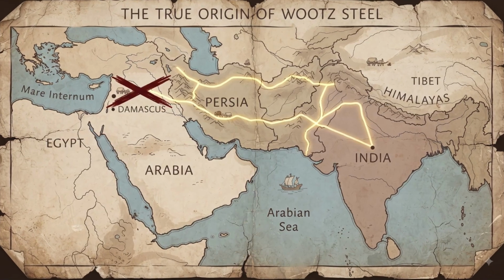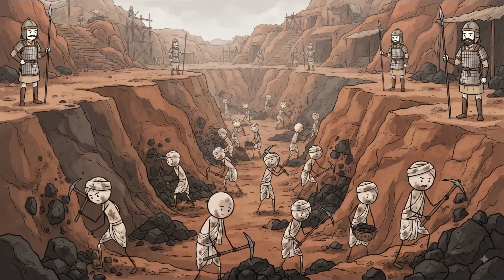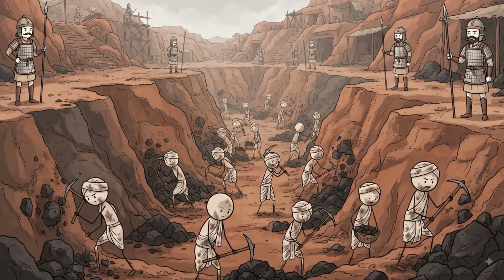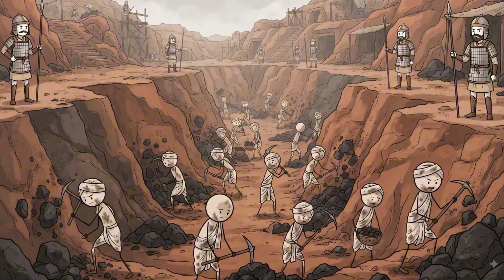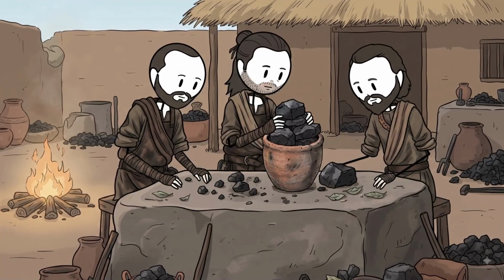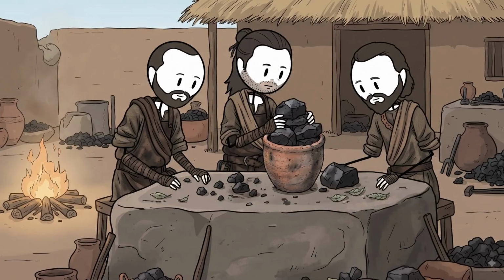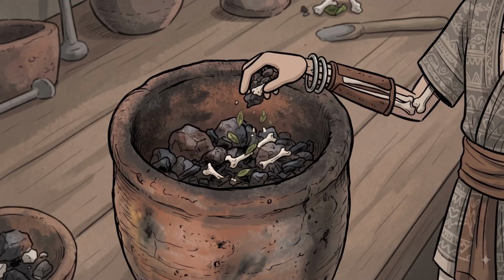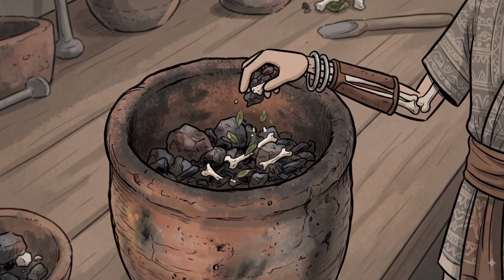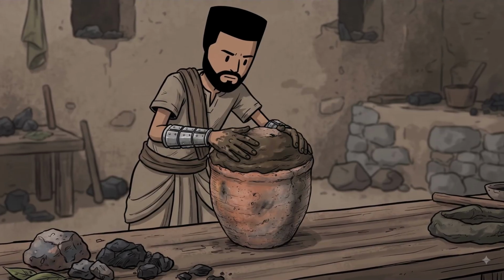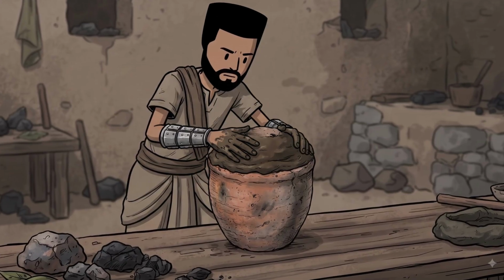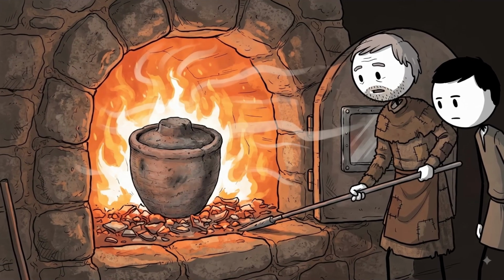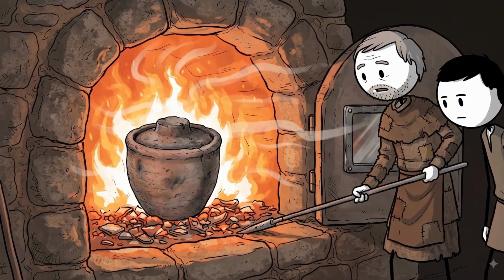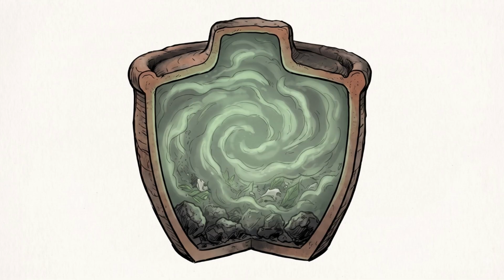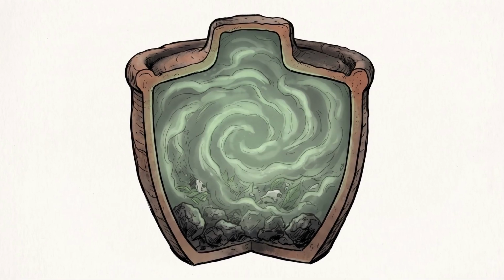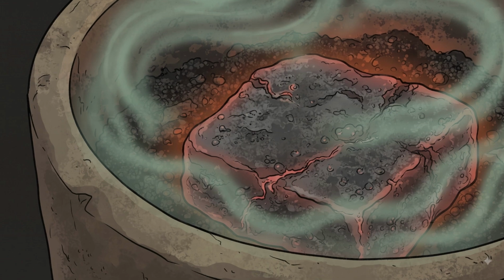The foundation of Damascus swords wasn't actually forged in Damascus. The raw material, known as wootz steel, was imported from specific, highly guarded mines in ancient India. The Indian metallurgists didn't just melt iron in an open fire. They engineered a closed-system chemical reactor. They placed the raw iron ore into a sealed clay crucible. But they didn't just add carbon. They added highly specific organic materials: leaves from the Cassia auriculata plant, woody stems, and sometimes even animal bone. They sealed the crucible entirely, depriving it of oxygen, and heated it in a specialized furnace to an exact thermal threshold of roughly 1,400 degrees Celsius.